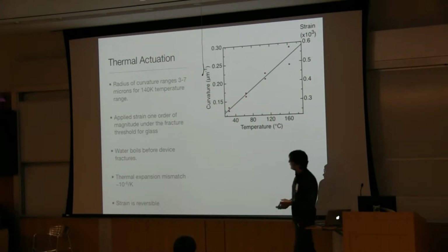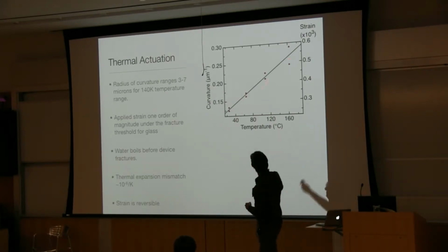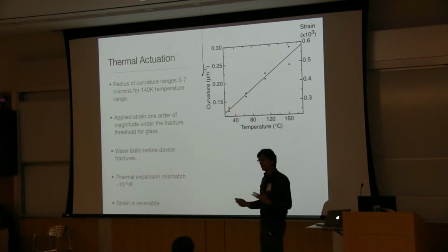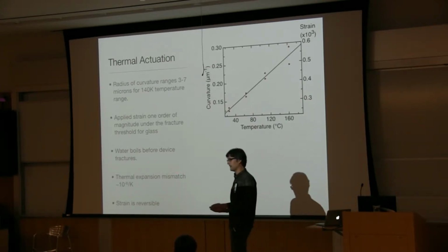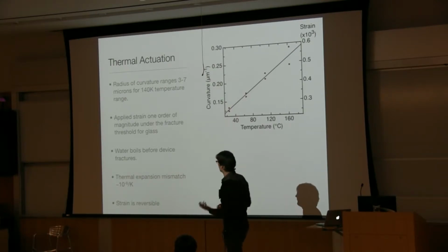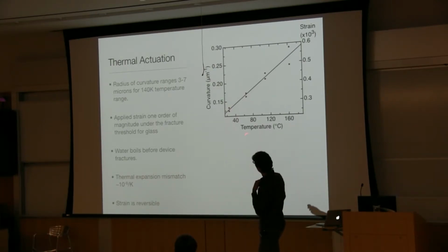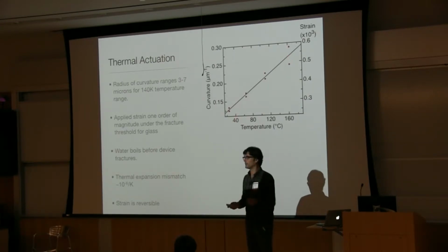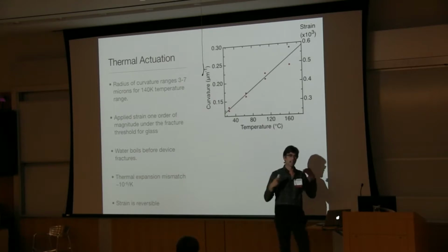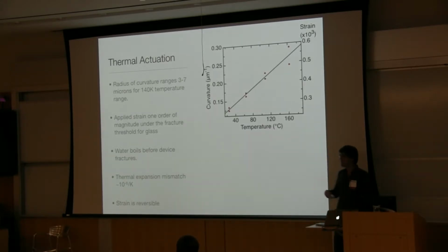And in fact, you can go and quantify this, and you find some interesting things. One is it is in fact linear. The relative mismatch in thermal expansions is about what you would expect. It's somewhere around 10 to the minus 6 in strain per Kelvin, so that's typical for hard materials like glass and graphene. The other thing that's amazing is even up here at about 165 C, so we can locally superheat the water because we're using a laser, we're still way below the fracture threshold for the glass or the graphene. So this thing's still behaving elastically even in this regime, and this data set is reversible forwards and backwards.